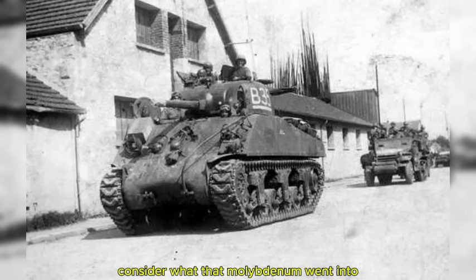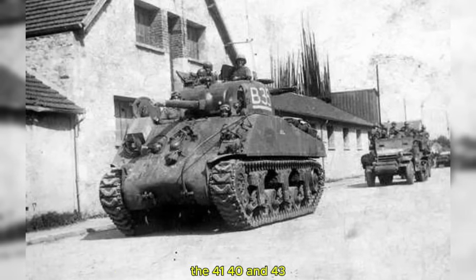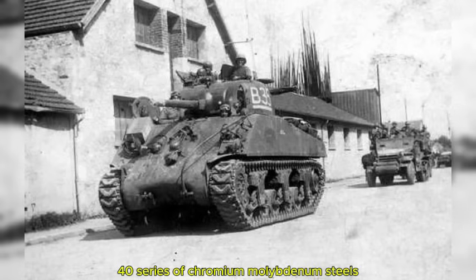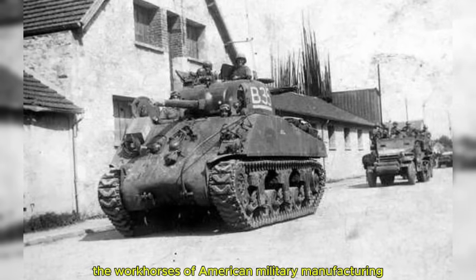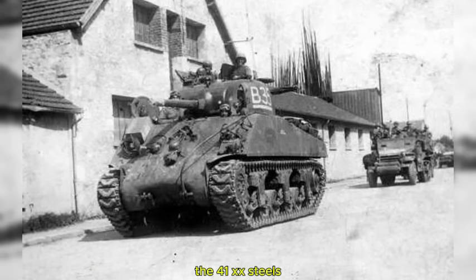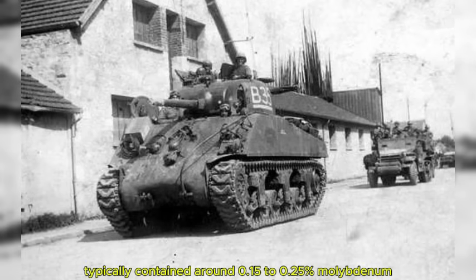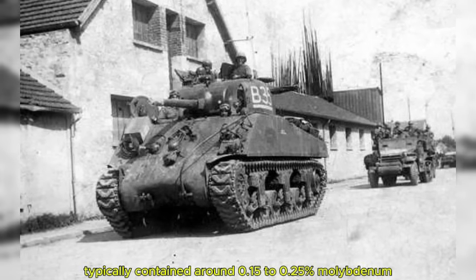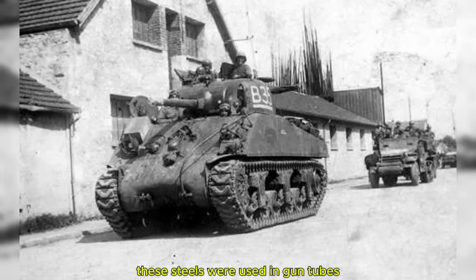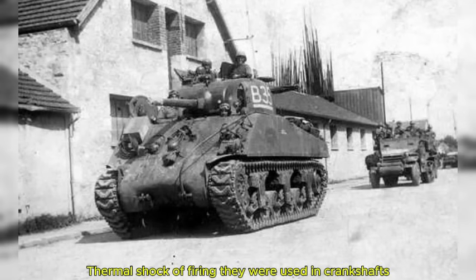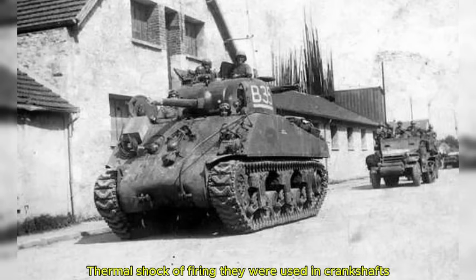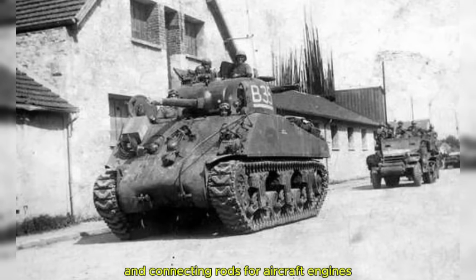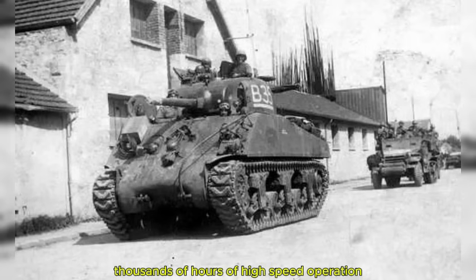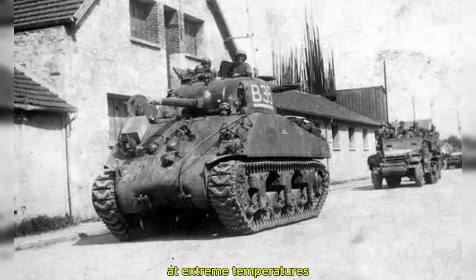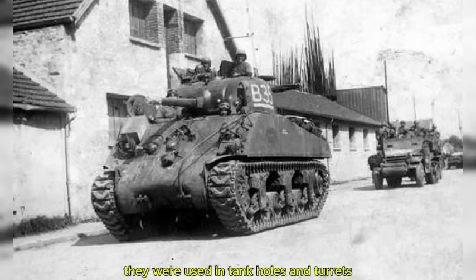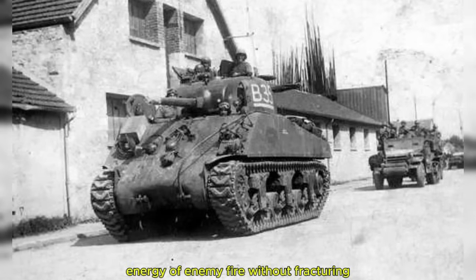Consider what that molybdenum went into. The 4140 and 4340 series of chromium molybdenum steels became the workhorses of American military manufacturing. The 41XX steels typically contained around 0.15 to 0.25% molybdenum. These steels were used in gun tubes where they had to withstand the repeated thermal shock of firing. They were used in crankshafts and connecting rods for aircraft engines, where they had to endure thousands of hours of high-speed operation at extreme temperatures. They were used in tank hulls and turrets, where they had to absorb the kinetic energy of enemy fire without